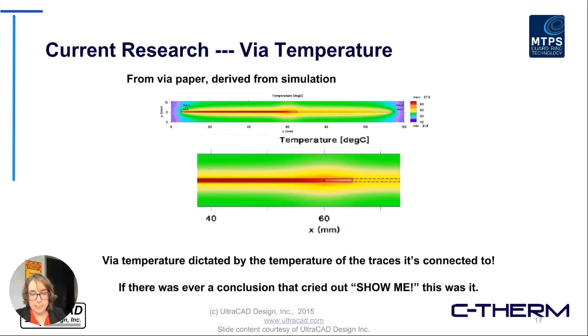So in the initial work that he had done, and I'm getting into why he came to us, he had modeled according to a 0.3 watt per meter Kelvin thermal conductivity of the board material. And what he got by his simulations here is actually that the via temperature, so the via here might be a little bit hard to see without a pointer, but if you look directly above the 60 millimeter mark on the lowest image there, you'll see on the red trace a little dot. That's a via in this finite element analysis model. The via's temperature is dictated by the temperature of the trace. It's not dictated by the amount of current flowing through it, which was really something that surprised him and his